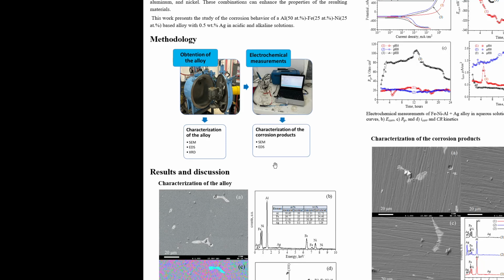In the results section, the characterization of the alloy showed two phases in the material: a predominantly homogeneous microstructure with grain size ranging from 50 to 100 micrometers, and a minor segregated phase distributed homogeneously within the microstructure, which are lighter grains, while the minority phase was primarily presented at the boundary of the larger grains.